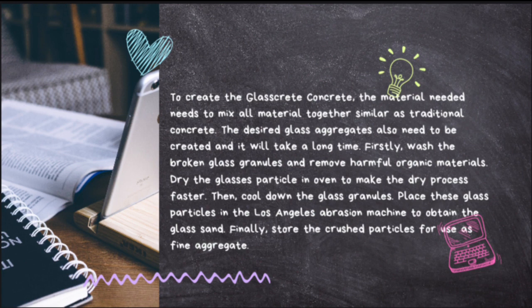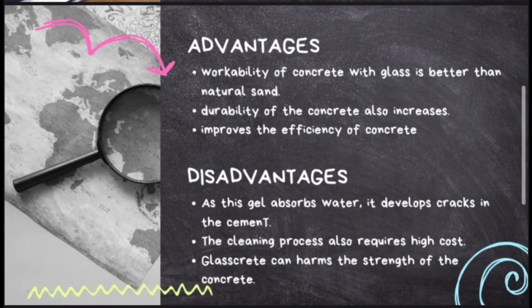Firstly, wash the broken glass granules and remove harmful organic materials. Dry the glass particles in an oven to make the drying process faster. Then, cool down the glass granules and place these glass particles in the Los Angeles abrasion machine to obtain the glass sand. Finally, store the crushed particles for use as fine aggregate. The advantage of this product is the workability of concrete with glass is better than natural sand.